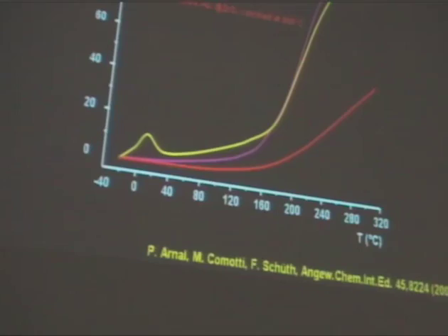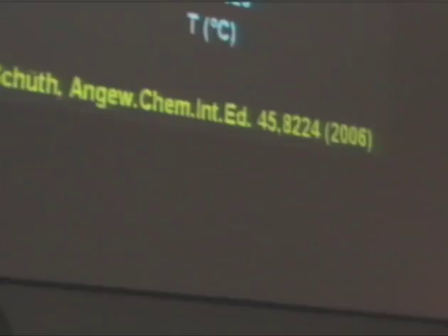And then just with sodium hydroxide, we leach the silica, and what you notice is that here the gold particles are in the center because they are suspended by the silica sphere. Here, the gold particles are basically just somewhere in the hollow shell because they fall where they want to sit. They are, in fact, sinter-stable. This is CO oxidation on these materials. The gold particles are rather big, so the conversion here reaches 50% only at 200 centigrade.